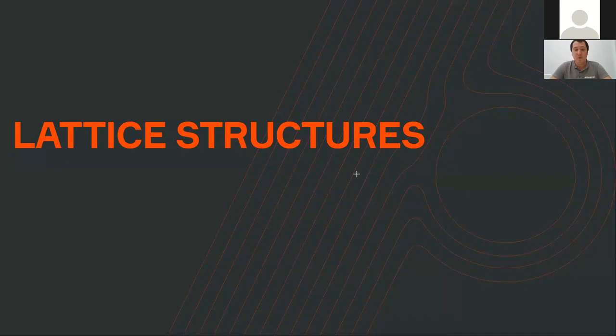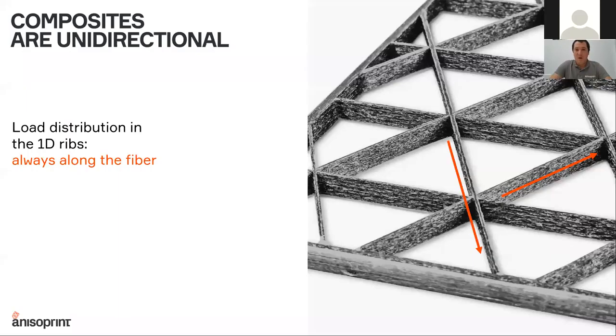So why? We now see that co-extrusion allows us to print lattices, and why the lattice approach is so important for us. The explanation is quite simple, and the reason is in the anisotropic nature of composite materials. All these high properties in the composite materials are along the fiber, and across the fiber direction, the properties are several orders of magnitude lower than in the fiber direction.